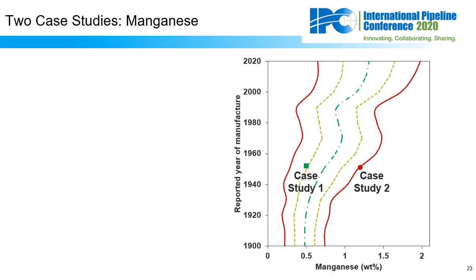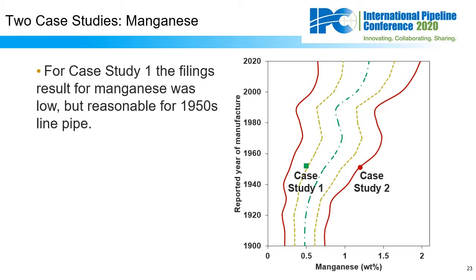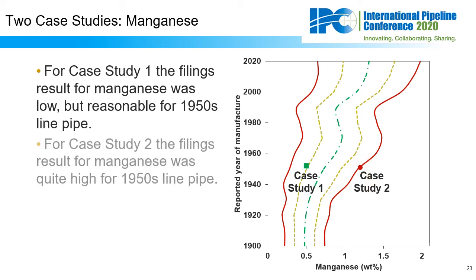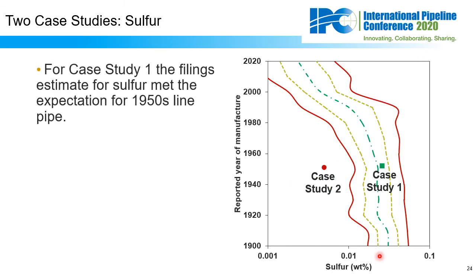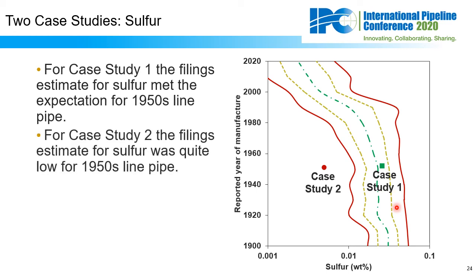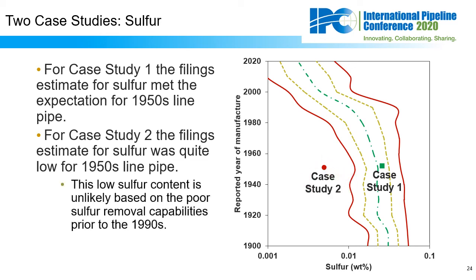Next, let's look at our composition data starting with manganese. We see for case study 1 for manganese that the value is low but reasonable, and case study 2, the value for manganese again is on the 2 standard deviation line. So it's quite high for the 1950s. Finally, let's look at sulfur. For case study 1, the filings estimate for sulfur is very close to the mean that would be expected for 1950, but for case study 2, the estimate for sulfur is way below the 2 standard deviation line. So this low sulfur content is very unlikely based on the poor sulfur removing capabilities prior to the 1990s.